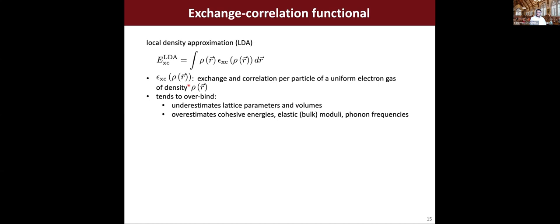This approach tends to overbind. So what does that mean? That means that our lattice parameters and our volumes are going to be underestimated, because it assumes that charge density is uniform around the system. And we know that there are systems, covalent systems being an example, where charge density is focused or clustered around particular regions in space. The fact that we're assuming the charge density exists uniformly everywhere is going to make our lattice parameters very small, because everything is more bonded than it should be. It's going to overestimate cohesive energies, elastic moduli, phonon frequencies,